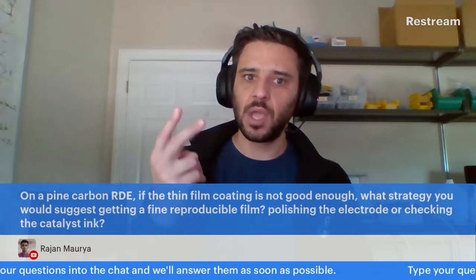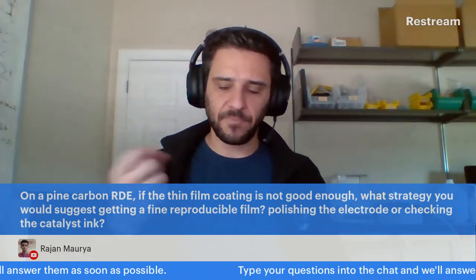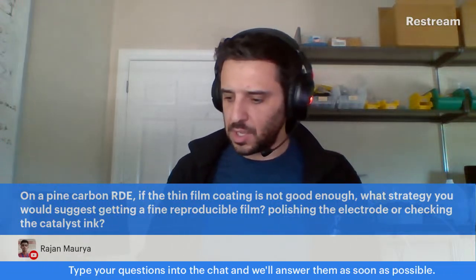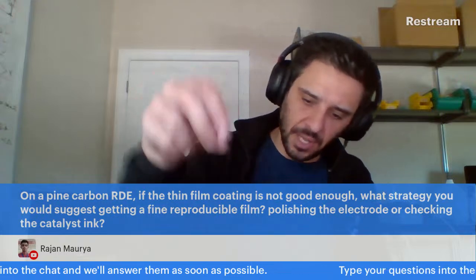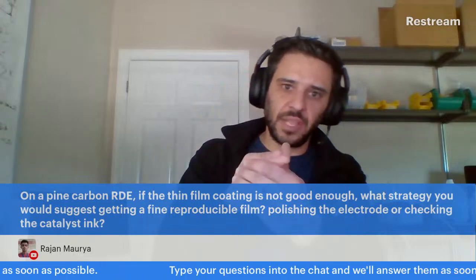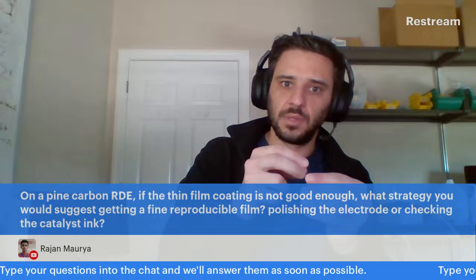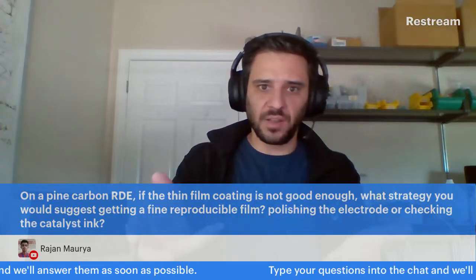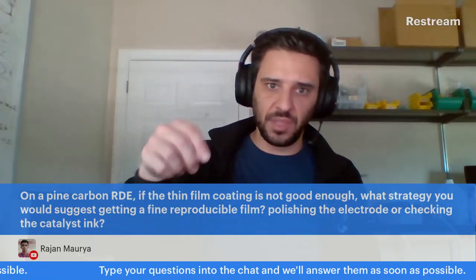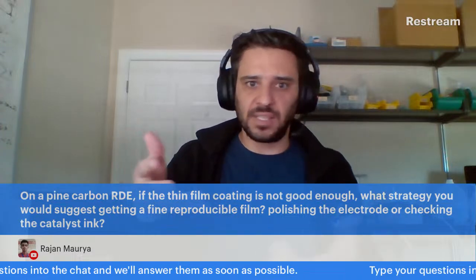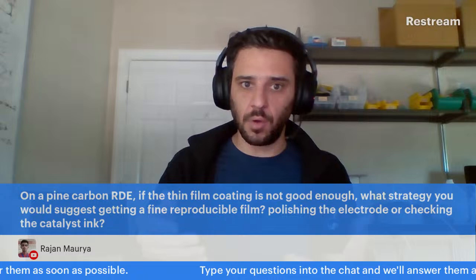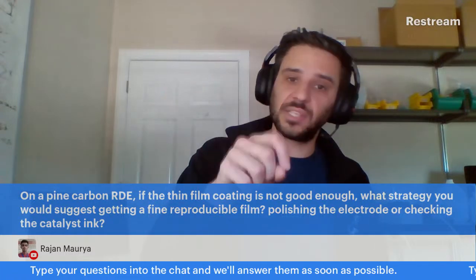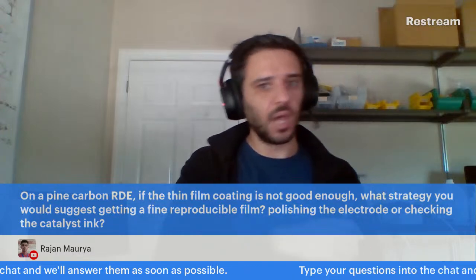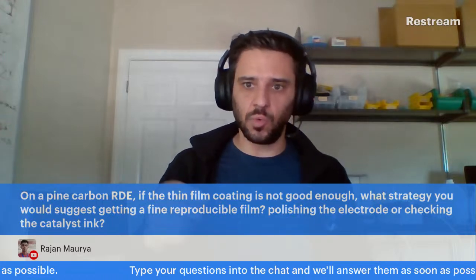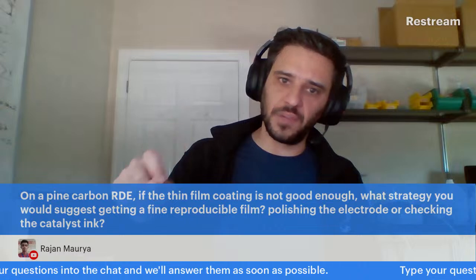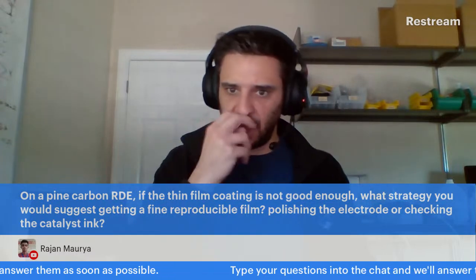Because it's a 2-step process. If you just do a 1-step polishing process, I always caution against this, because if you get your pad, you put your slurry and you start polishing your disc, you have slurry and some water, and you have the film, and it's wiping it off the surface. But where is it going? It's going into the slurry, right? So you are polishing with the remains of your old film. Is it going to re-stick on the surface? Maybe, maybe not. Hard to know. So if you have 2 steps, use a different place on the same pad or a different polishing pad altogether, a fresh amount of alumina, you decrease the likelihood that any of your old film will still be there. So that's the first thing that I suggest.